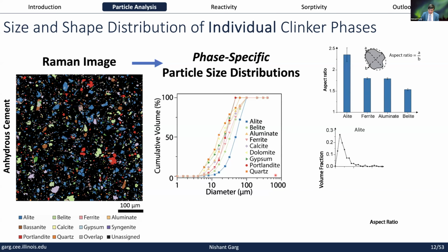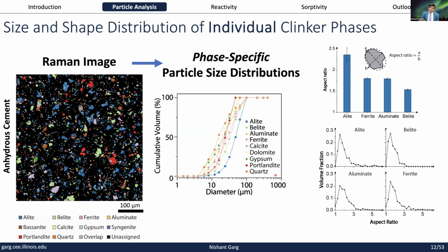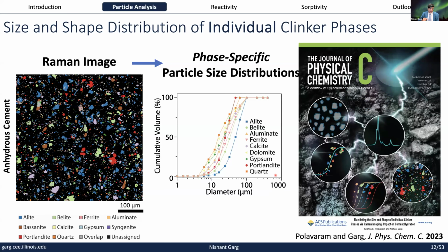Of course, you can look at other things such as the aspect ratio and volume fraction. All of these can be picked up from that size and shape analysis, depending on the resolution you use for your scan. And this work came out a couple of years ago on the cover of JPCC, so I think we were very proud. I think this really starts off a new era where you can look at both the size and the shape and the quantification on a single material with a single technique.